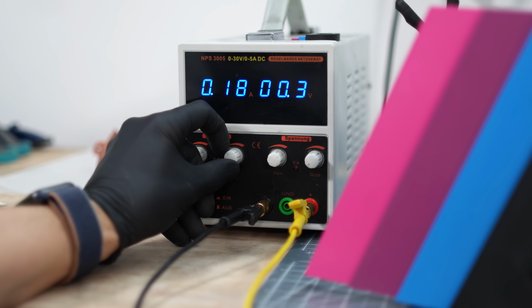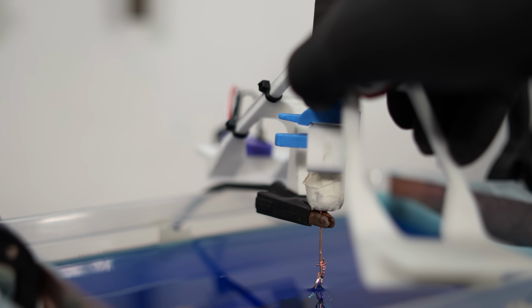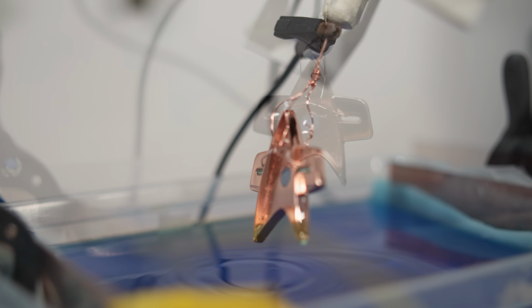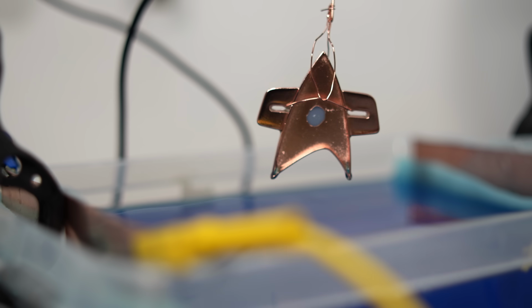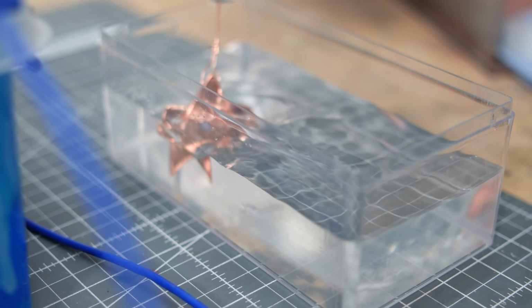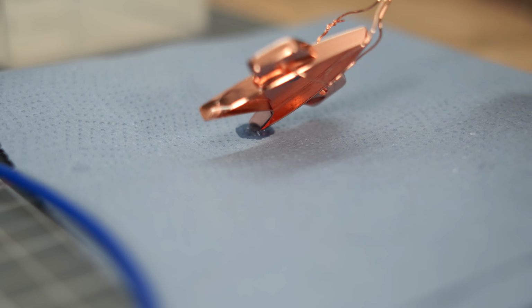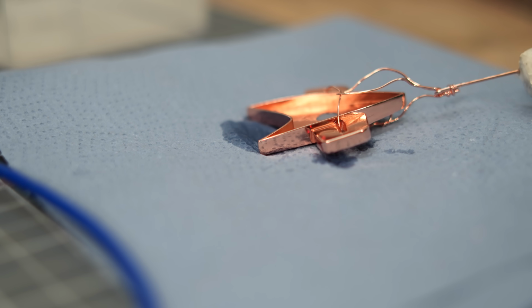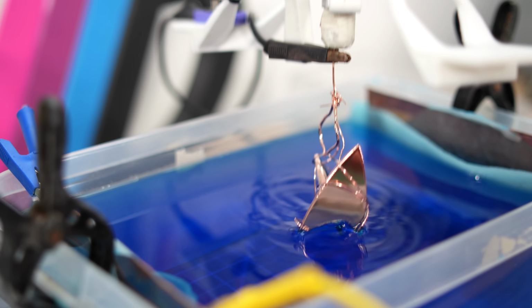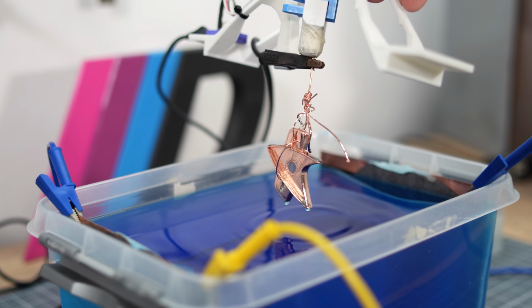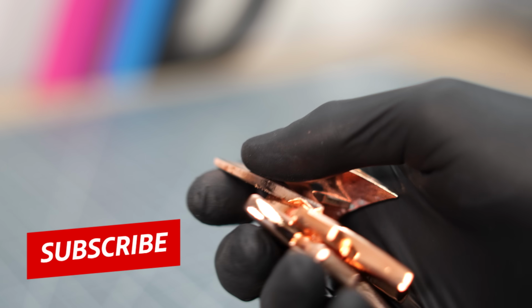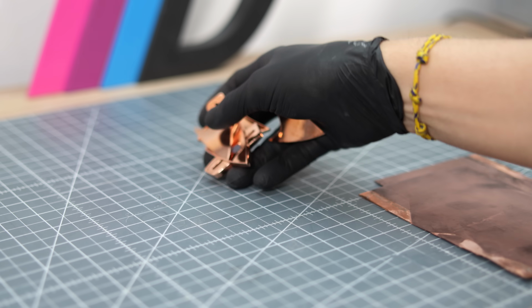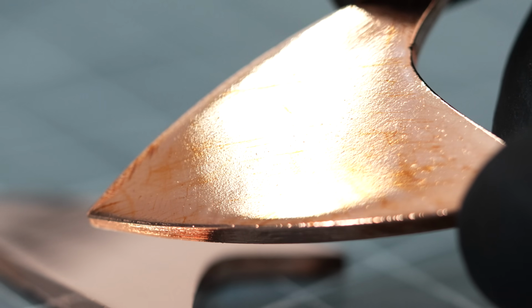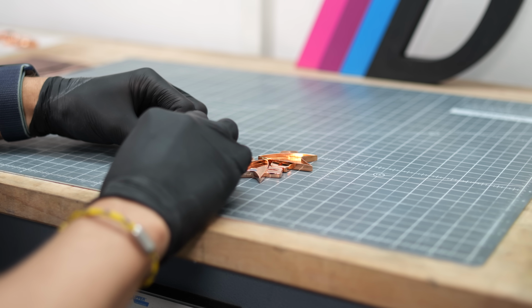Turn up the current and set it to the target value. Then simply wait for 4 hours and afterwards you'll have a quite thick layer of copper on your 3D print. After that, wash it thoroughly in water and let it dry quickly. All remaining parts are produced in the same way. It already looks great. Now the pieces can be finely sanded with the finest sandpaper.